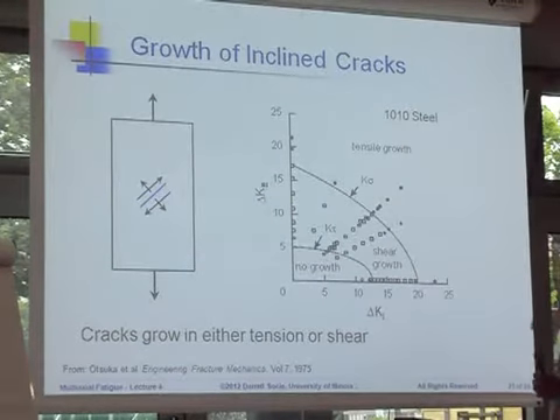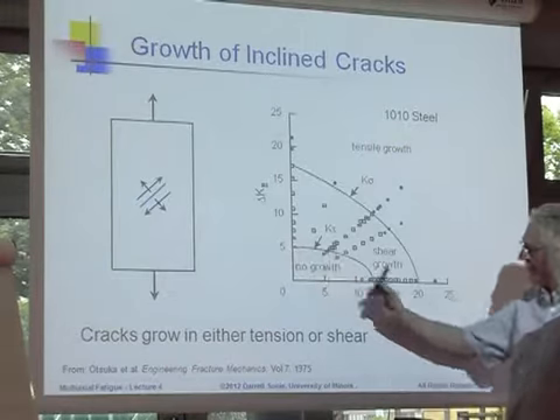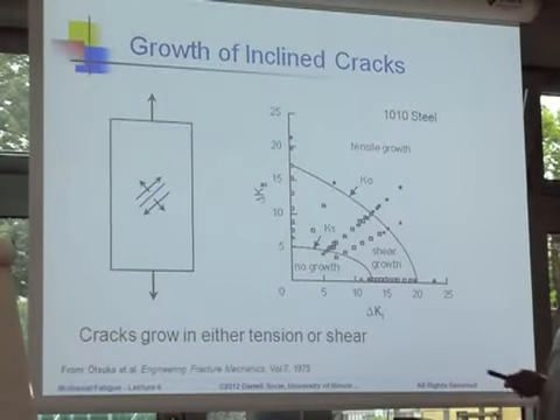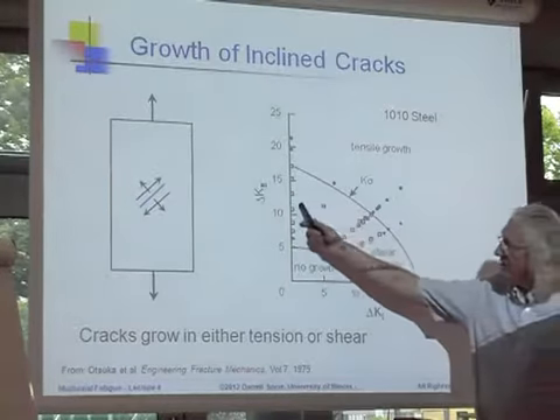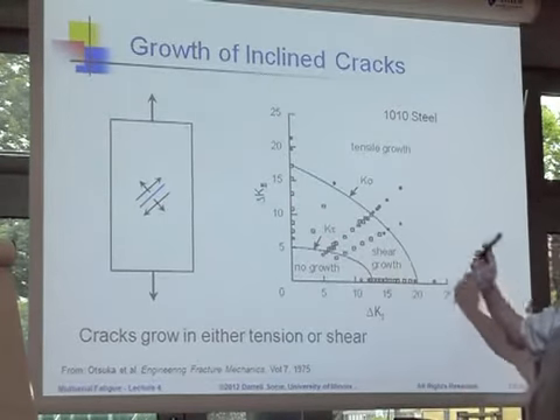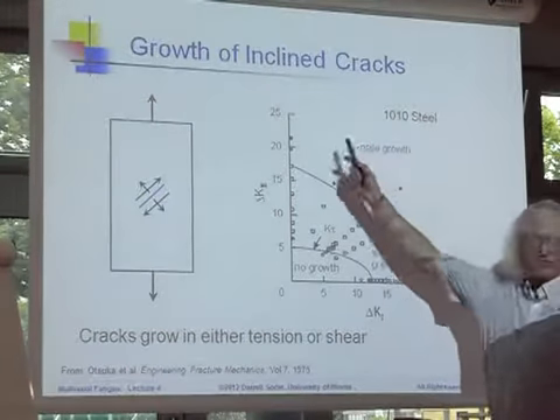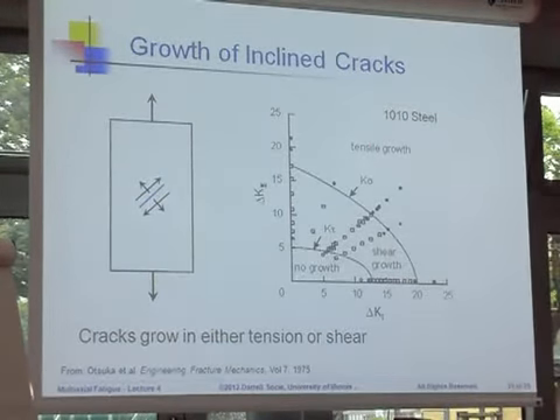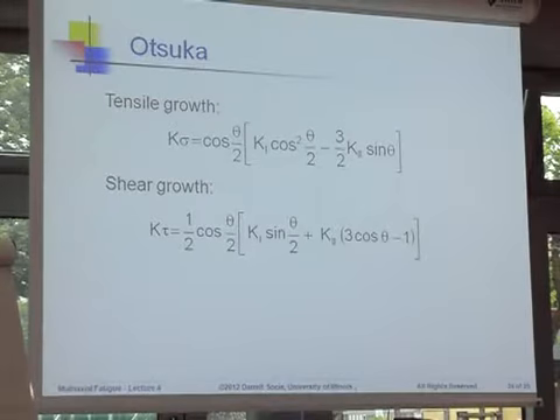And what you actually find is, of course, when these values are small, nothing happens. And then you can have a region for which you always get growth in shear, right, at the very low stress levels. And then as you go to higher stress levels, then you always get growth in tension. And his idea is, if I want to know if I have tension or shear growth, I calculate a tension and a shear stress intensity. Basically, I can work out the stress intensity factor in any direction that I like, so I work it out in the direction of the maximum principal stress, and I work it out in the direction of the maximum shear stress, and from that I can tell what the expected growth direction is.